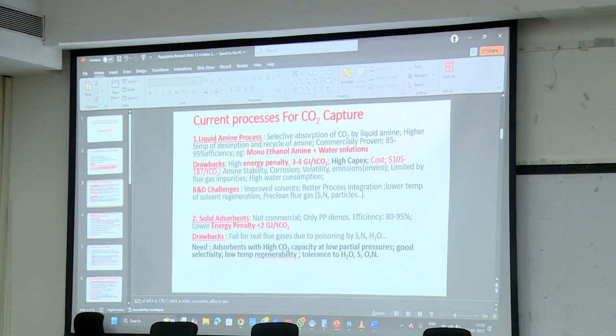Amine stability is another factor. These amines decompose because many of these flue gases contain oxygen, nitrogen, NOx, SOx and so on. Amine stability, corrosion, and toxic materials are issues, with leakage of amine into the plant being a real problem. The emissions are limited by flue gas impurities and high water consumption. The R&D challenges in this process are an improved solvent, one which does not decompose and has a lower temperature of desorption of carbon dioxide, better process integration, lower solvent regeneration temperature, and pre-cleaning of the flue gas.